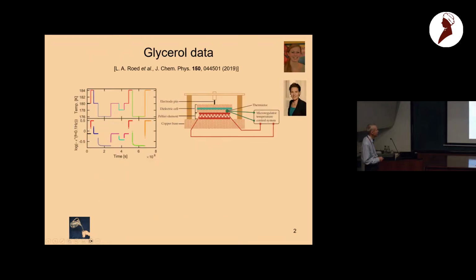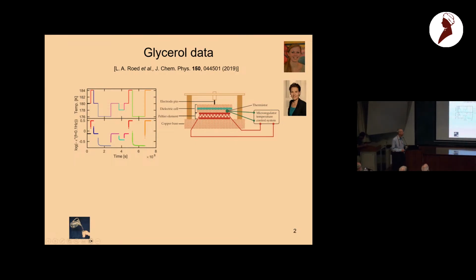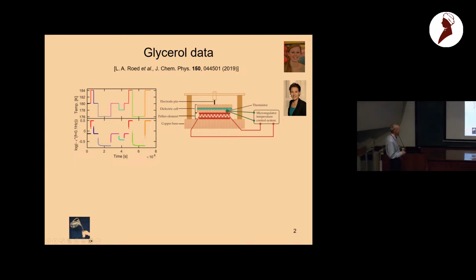So these are data by Lisa and Christine. This is our setup where we have basically just a capacitor measuring dielectric signal and a 50 micron liquid here. These are very long experiments on glycerol published some years ago. So this is, I think, something like 3 months of experiments. And what we do is that we change temperature and then we equilibrate, and then we change temperature up and down in different ways. And you can see the measured signal here.